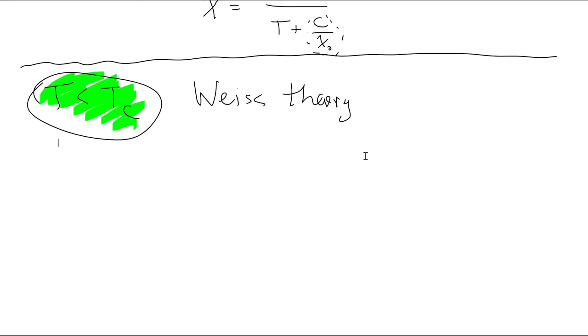below Curie temperature. Okay, so at low temperatures, basically what we have is our magnetization would be equal to MA, and if we disregard the direction, minus MB, so that magnetization value would be equal to the difference of the two sublattices. So below Curie temperature, everything becomes ordered. You have antiferromagnetic order of two sublattices which have different magnetizations. And as I already drew, one points up, the other one points down, and the resulting magnetization M is their difference.